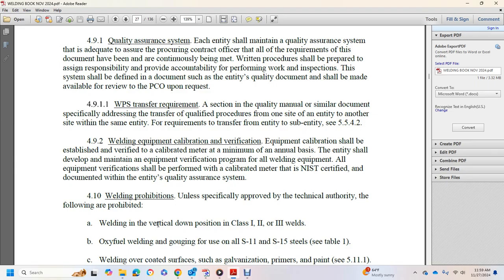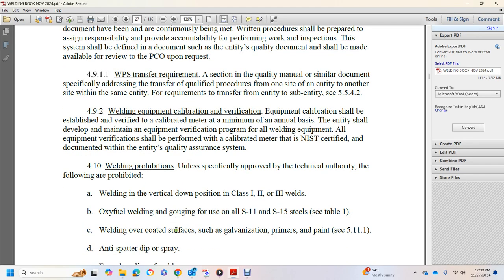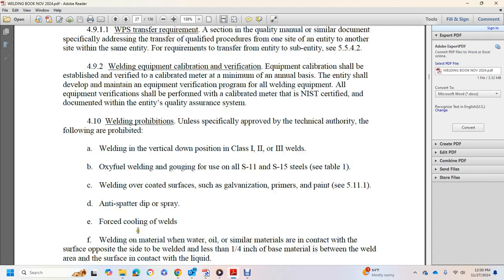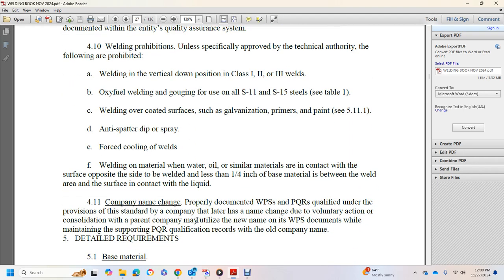Unless specifically approved by the technical authority, the following are prohibited: welding in the vertical down position on Class 1, 2, and 3 welds; oxy-fuel weld gouging with S11 and S15 steels; welding over coated surfaces such as galvanized, primers, and paint; anti-spatter spray; forced cooling over the welds; welding material with water, oil, or similar materials; or contact surface on the opposite side of the weld with less than quarter-inch base material between the weld and the contact surface.